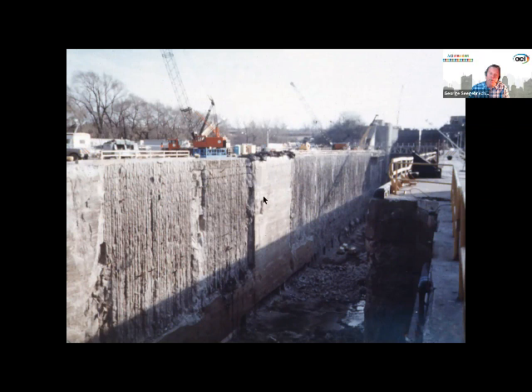But when you read the paper that Ron Kozakowski wrote about winter strategies, it'll make you think about how much protection is really needed and what's best to do. Just let the concrete warm the subgrade, or if there's any massive metal, not there, just minor rebars, just hairpin this to the side, or do you heat the forms and the concrete and then keep it heated after that? It's very interesting to compare 3 scenarios that they use before the concrete and the substrate or the steel come to equilibrium, and from the standpoint of the contractor, it makes a big difference in terms of